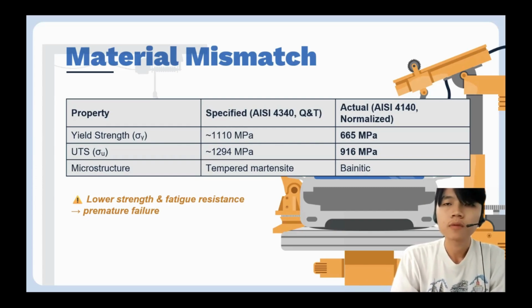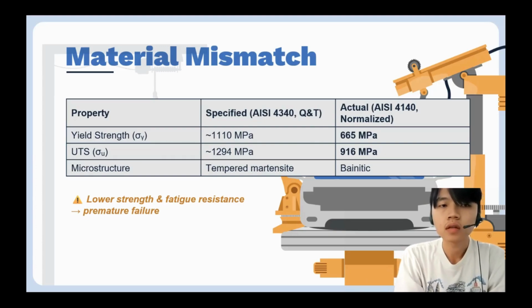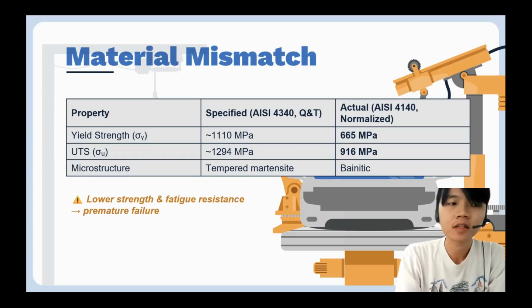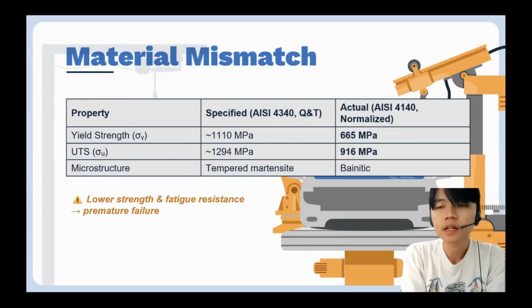Similarly, its ultimate strength is also much lower. And if we look at the microscopic level, the 4340 would have formed a tempered martensite structure, but 4140 only produced a bainitic structure with weaker mechanical properties. So this material mismatch meant that the shaft simply could not withstand the stress that it was designed for.